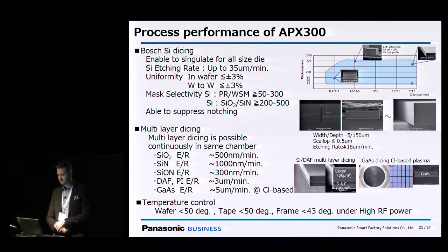So taking a little more detailed look at the processing capabilities from a silicon point of view, so dicing speed can be around 30 or up to 35 micrometers per minute. Uniformity on the wafer itself is less than plus minus 3%, and also wafer to wafer at the same level. So then we also have different selectivities available, whether you use a photoresist or a hard mask. Then here are some examples of different dicing speeds if there's different layers in the wafer. So sometimes half a micrometer per minute. Gallium arsenide, I think, is also important for today. We're using chlorine-based gas around 5 micrometers per minute.